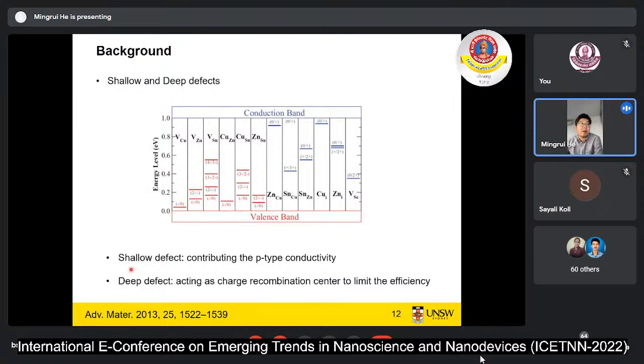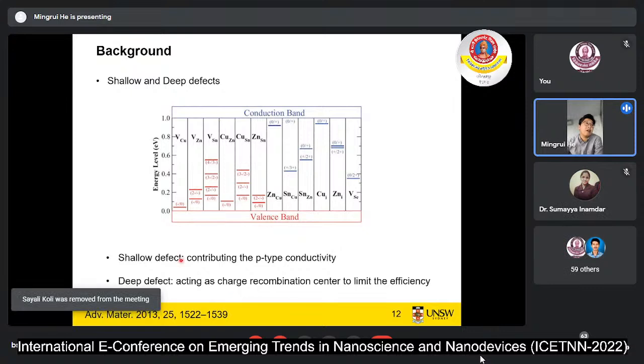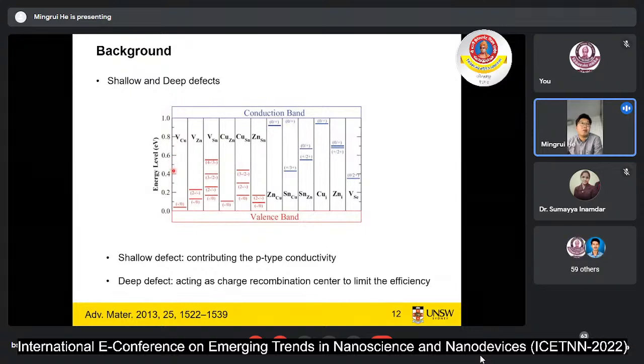This is one of my topics today. I did some engineering on the shallow defects, in which I changed the copper zinc anti-site defect to another defect. In addition, I would like to mention that for the shallow defects, copper vacancy and copper zinc anti-site, it is normally quite difficult to get the copper vacancy defects because the formation energy of this defect is a little bit higher than the copper zinc anti-site defect. So if we have some method to form this kind of defect, it might also be good for the kesterite materials.